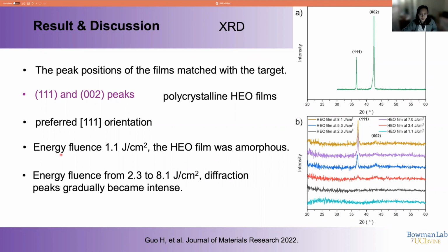So the fabricated films have the preferred 111 orientation. And the energy fluence will change the crystallinity of the fabricated films. At the low energy fluence, you can see there are no diffraction peaks. It's just some amorphous area. But with the increase of energy fluence, the diffraction peaks occur gradually, and the intensity goes higher with the increase of energy fluence. So that means at higher energy fluence, the crystallinity of the HEO films is higher than that fabricated at the low energy fluence.